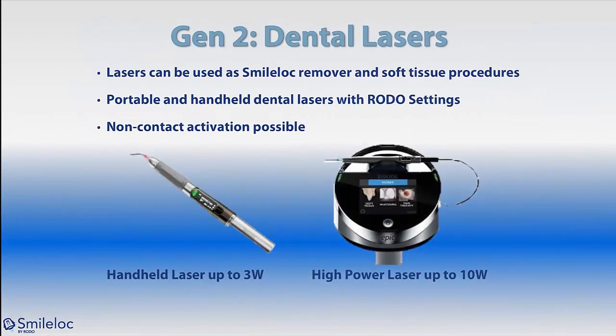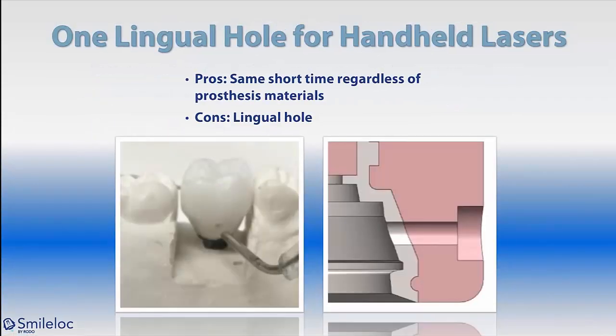Second generation was the dental laser. It was portable and handheld. There was non-contact activation possible if the laser was powerful enough. But the handheld laser, which had 3 watts of power, required one lingual access hole, as you can see here. Same short time regardless of the prosthetic materials to remove it.